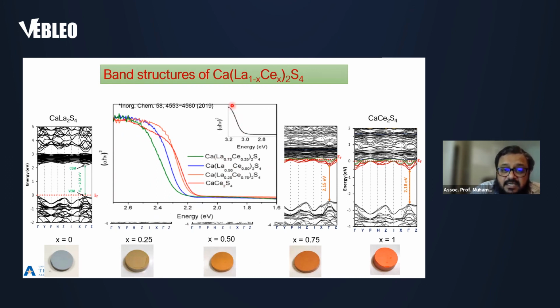As you can see, the optical absorption starts somewhere around 3 electron volt. Another thing that I would like to point out quickly is the bands near the conduction band or near the Fermi level with higher cerium concentration. We see that there are some partially occupied or fully occupied bands around this conduction band continuum. We'll look at this closely in the next slide.